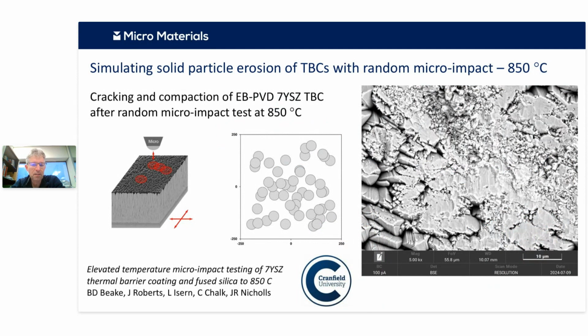And what you can see on the right is the surface of a thermal barrier coating that's been impact tested, in this case at 850 degrees C. And this sort of cracking and compaction is similar to what you see in eroded samples.